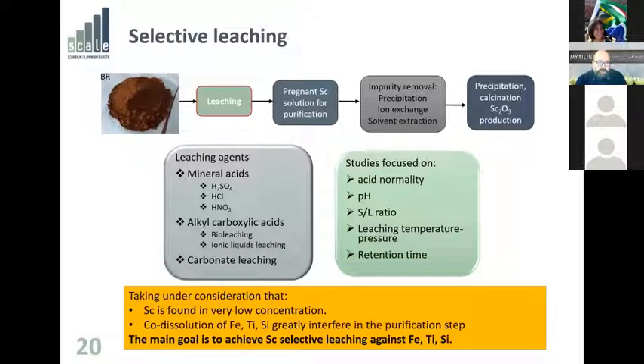There has been use of organic acids. There are reports, several papers on bioleaching, and some interesting work even on ionic liquid leaching. And finally, there's also a carbonate leaching, which I will explain a bit later. And all the studies here focused on changing the amount of acid, controlling the pH, the solid to liquid ratio, leaching temperature, and pressure and retention time.